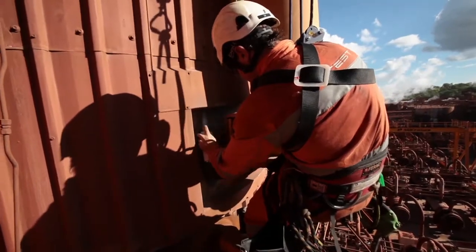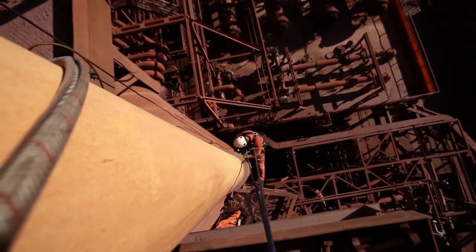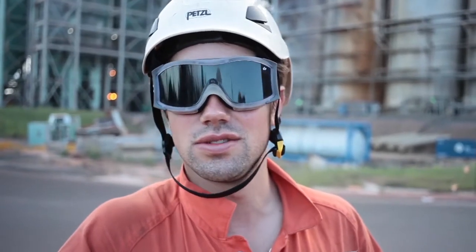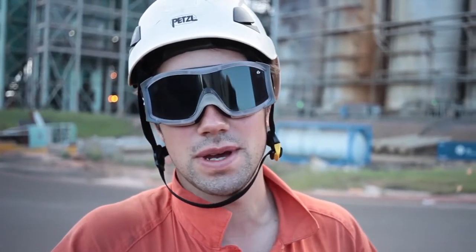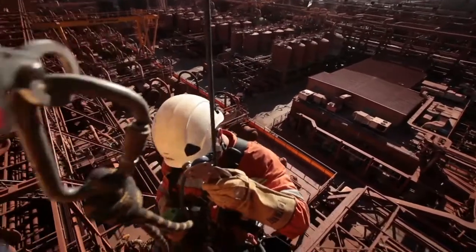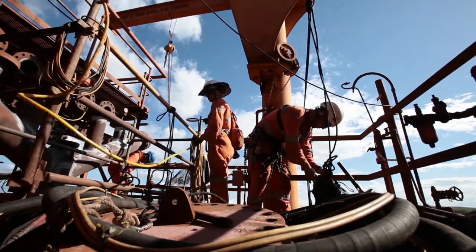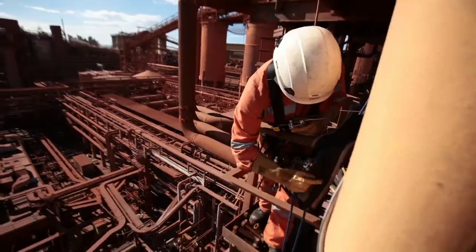We were looking specifically for cracks, so surface cracks, so we're MPIing. Magnetic particle inspection, we do our UT, ultrasonic, where we send a sound wave through and look for responses that come back. And we also do dye penetrant. So again, where the client has in the past had to scaffold out large tanks, we're able to access it with rope access right at the designated sampling locations or test locations. We can go in there, sandblast prep, and then do the NDT inspections.